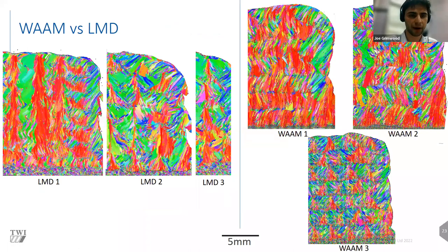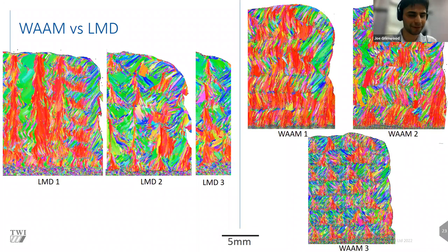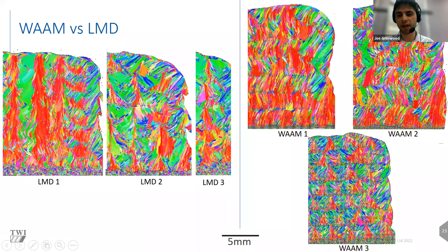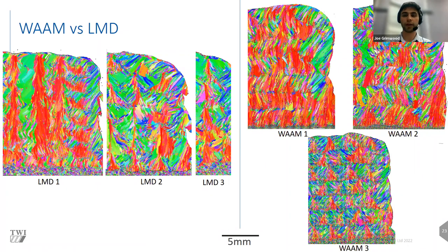Focusing on one orientation: comparing three LMD builds and three wire arc builds, each using different parameters, the differences are quite striking. In one LMD build, you have really large columnar grains with red grains dominant in one region and green grains dominant in another, running pretty much all the way from the bottom to the top. Contrasting this with the wire arc bottom-right image, you see a very different structure — almost every single deposited bead re-nucleates a separate grain structure, giving much finer, more equiaxed overall grains.